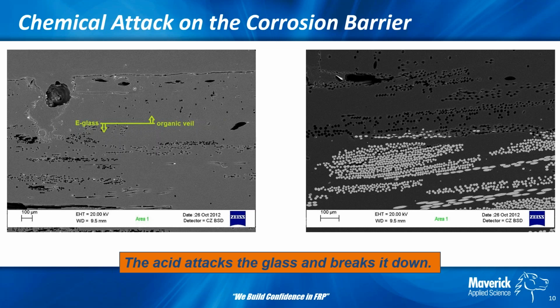So let's talk about the chemical attack. Here's some more SEM, and you see the green line that we have here on the left. This more or less defines the boundary between the veil layer, which you see pointing to the top here, largely going to be what would have been a glass veil. At this time, more than 90% resin probably. And then below the green line, this is where you're getting into your chopped strand mat layers.